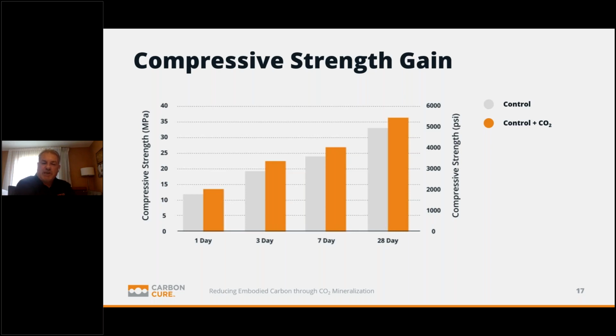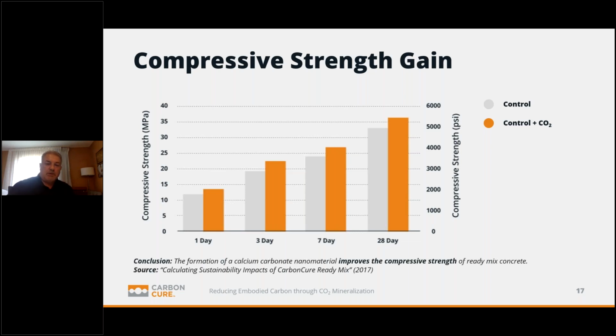So this is just an example of a chart that we would see from some typical testing that we would do with the producer. The bar on the left is the control. The orange bar on the right is the sample that has CarbonCure incorporated into it. What we'll typically see over those testing periods, when we break the cylinders at 28 days as an example, is a strength gain of up to 10%.